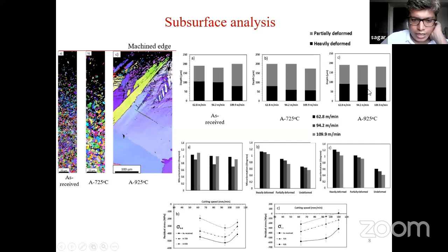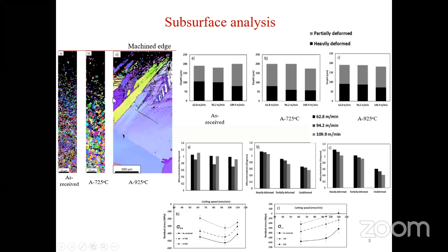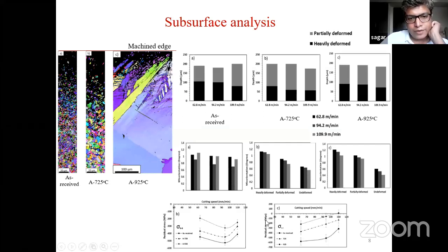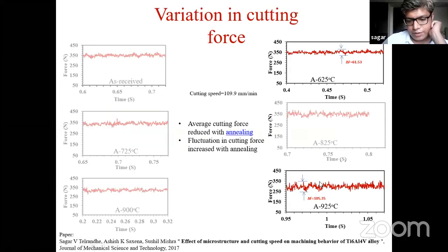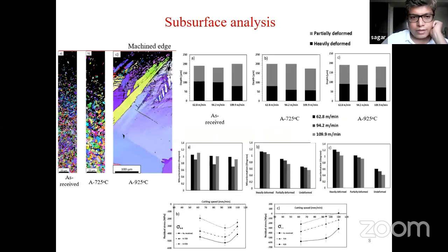Even the residual stresses have been reduced for the highest grain size sample. That we have seen, means these residual stresses are directly proportional to the cutting forces. So we have seen that average cutting forces have reduced over here, because predominantly the grain size has been increased, and that has reduced the hardness of the sample, because of which you get lower average cutting forces. Although you get lower average cutting forces, you still have higher variations in those cutting forces.